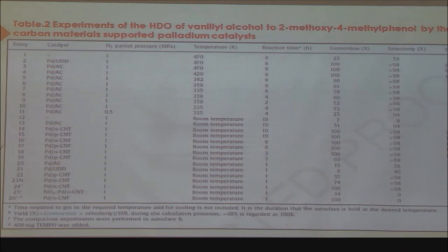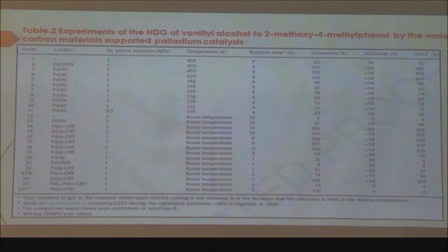What we do is we take the catalyst, we take the lignin, and we put it in a reactor where you can purge the hydrogen, and you heat it, or you don't heat it, at room temperature. And you analyze the products, what the products are. Before doing it on the carbon material, we just take an organic molecule, vanillyl alcohol. Vanillyl alcohol is an aromatic compound where you have OH and OCH3 groups attached to it. We really want to see this, because these are the functional groups in lignin also. So we just want to do it before lignin on some organic molecule, where such a reaction, very close to lignin, can be studied.